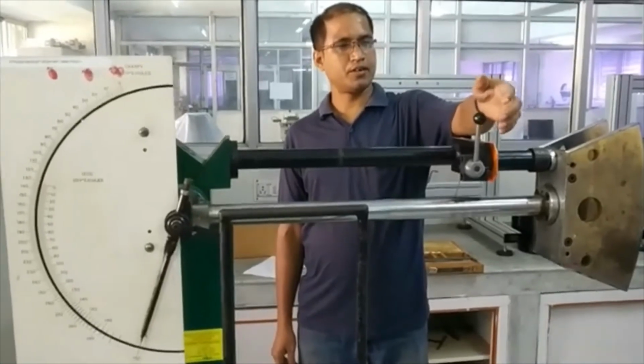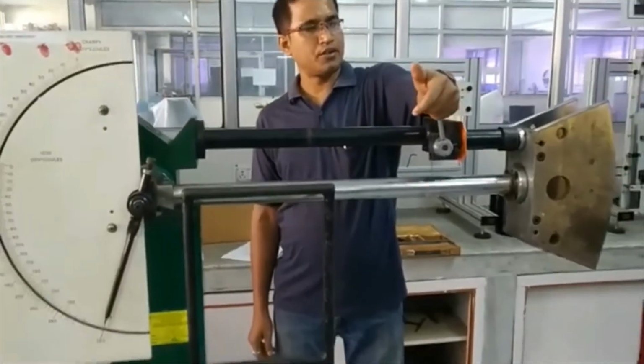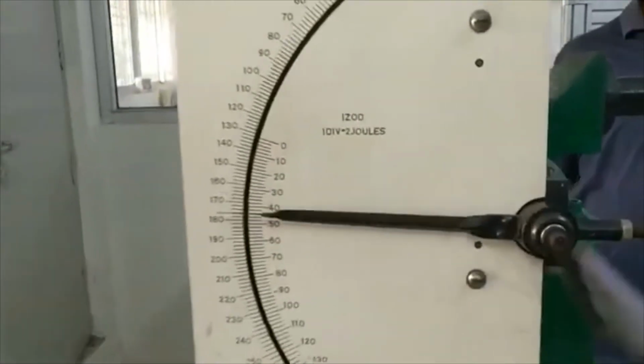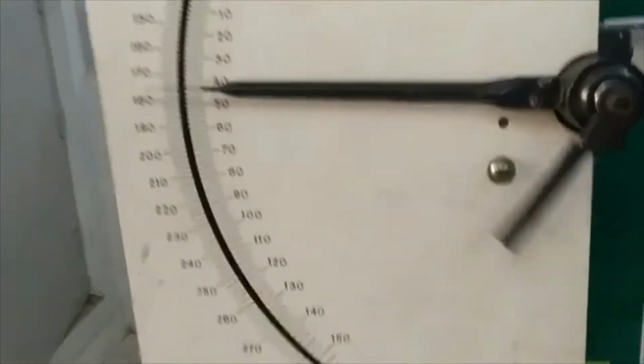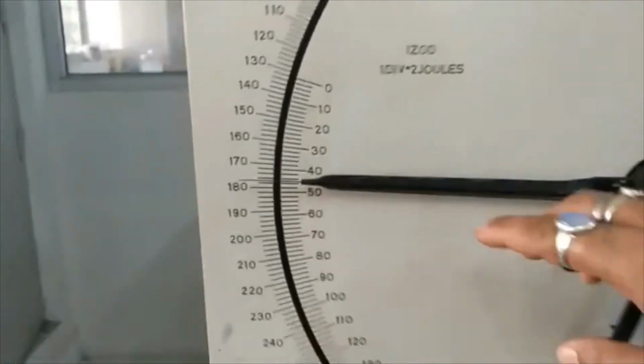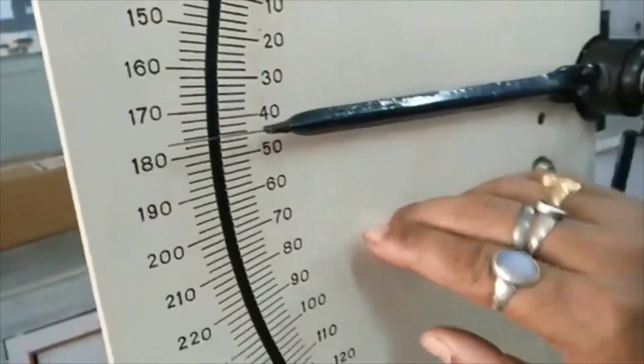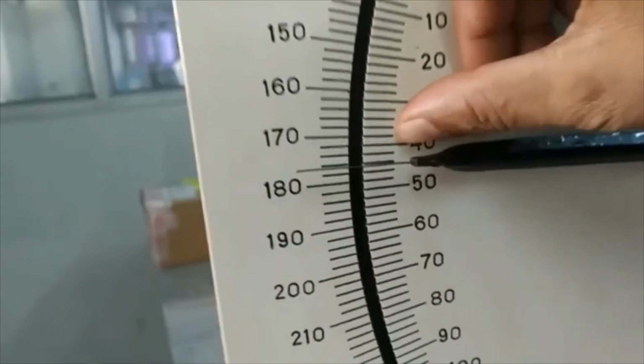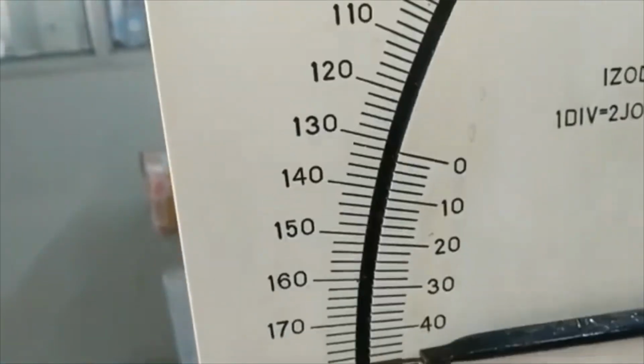Now let us release the hammer. So we will release the hammer. So now we have seen the hammer impact the specimen, and the specimen broke. How much energy is absorbed, you can see directly from this dial gauge. Where the pointer is, you clearly see 40 joule, 42, around 44 joule. 44 joule energy absorbed. Now we will remove the specimen.